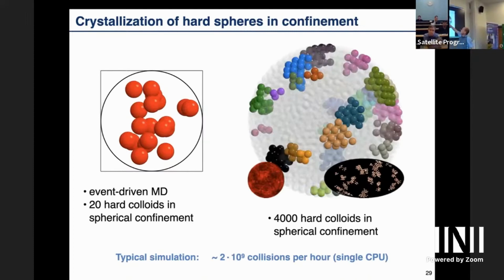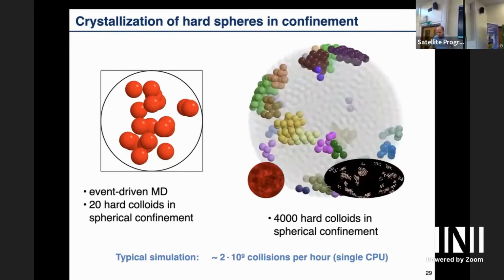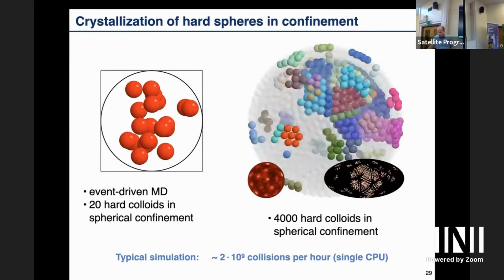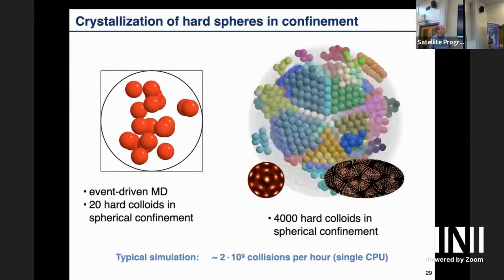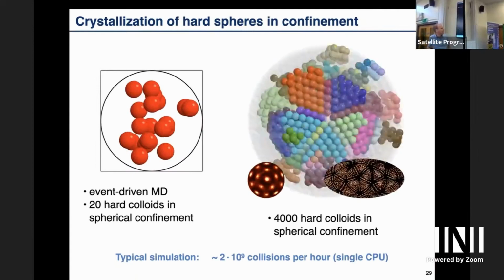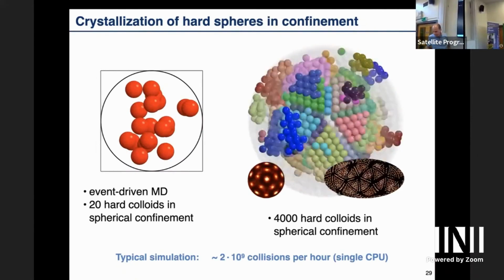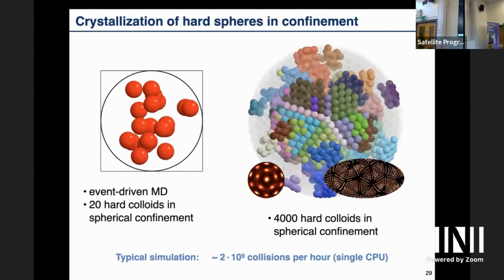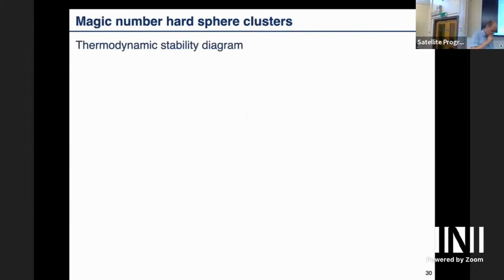So this is sort of at the beginning where we have some grains, but it's not perfectly ordered. And as I run it, you will see that the grains will grow. At the beginning it fluctuates, and then over time you see sort of a crystallization of this icosahedral cluster. And we analyze this process a lot. Due to time constraints, I will not have full time to talk about all the aspects, but those of you that are interested should just talk to me separately. But I will show you some other things we can do.